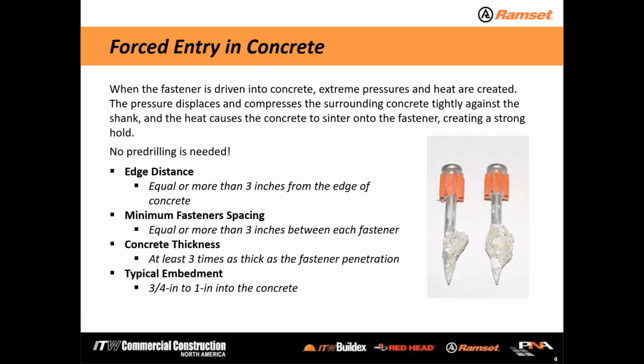So generally, with a lot of applications, we'll go 1 inch worth of penetration. So the concrete must be at least 3 inches deep. If the concrete's not at least 3 inches deep, what will tend to happen is that driving action will blow out the back side of the concrete. So we want to make sure we have enough thickness there as to not blow out the back side or crack the base material for that matter on that driving action.